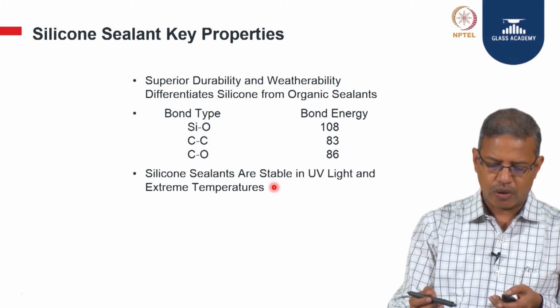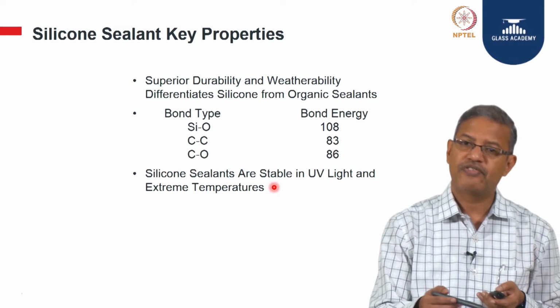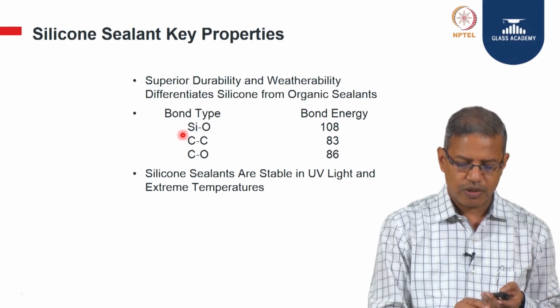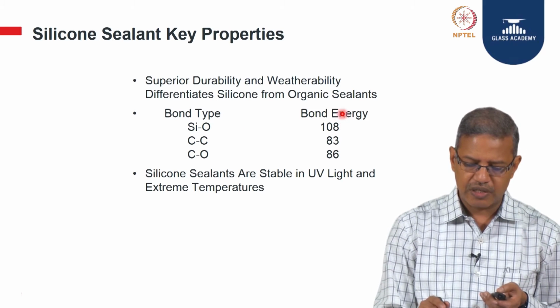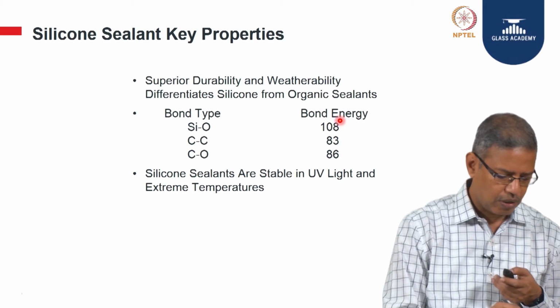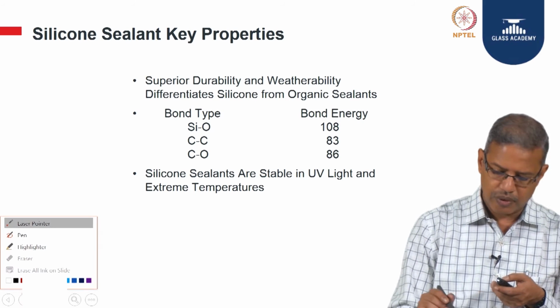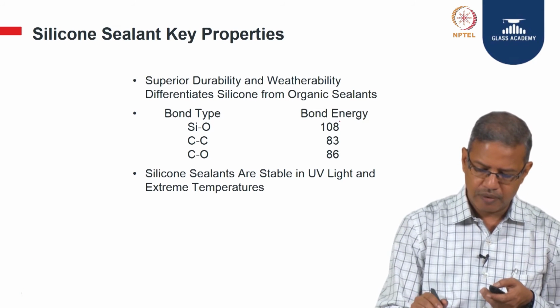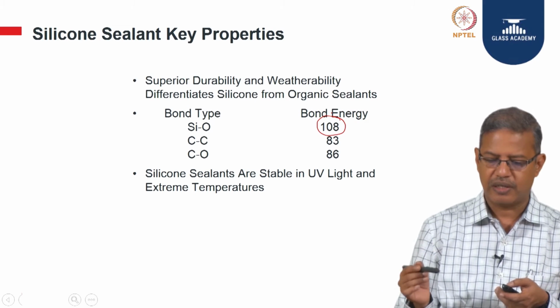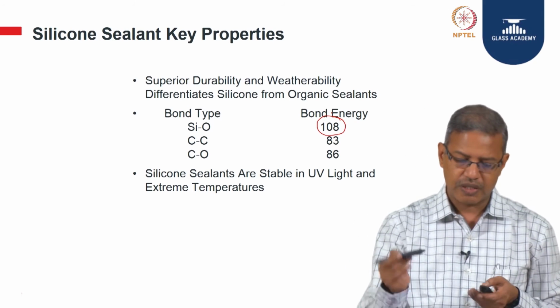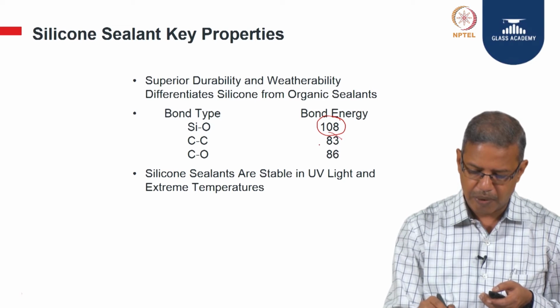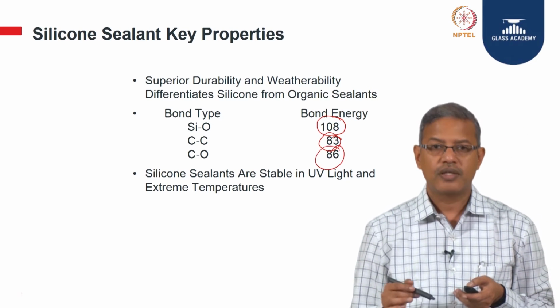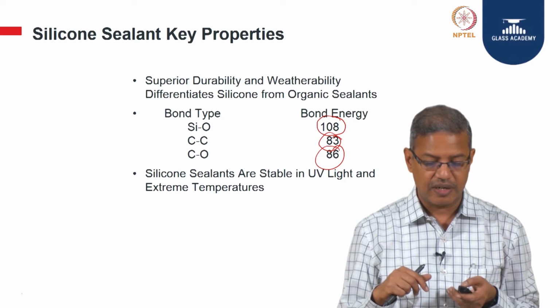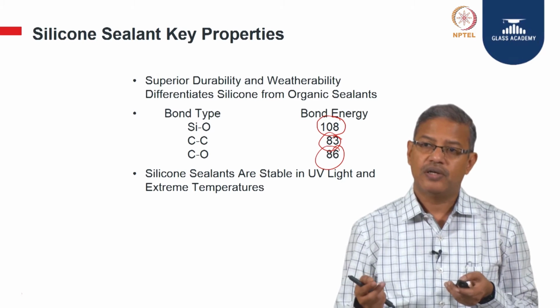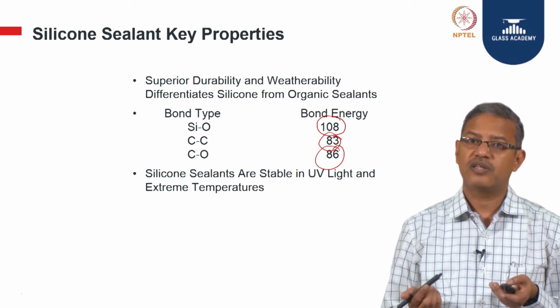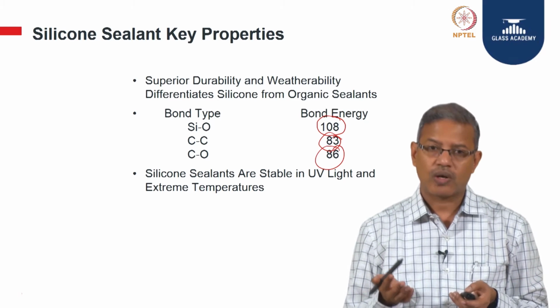This slide talks about the bond energies of different materials and different chemistries. The first one is silicon oxygen, and you can see the bond energy is 108 kilocalories. This is much higher than the UV in the sunlight energy, which is around 90. If you look at carbon or carbon oxygen, they are all much lower than the UV in the sunlight energy, and they get degraded with time. That is the reason you do not get much durability with organic sealants.